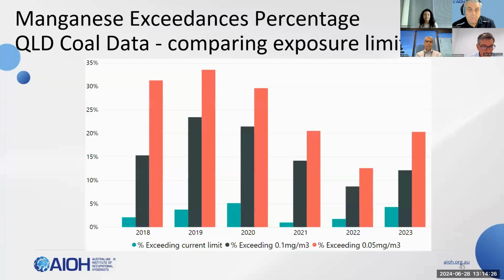If we then look at the proposed limit that comes into effect in December 2026, in black, which is 0.1 milligrams per cubic metre, you see it goes from about 15 to 20%. And if you then look at, as I mentioned earlier, the rule of thumb, good hygiene practice of controlling exposures to 50% of the OEL, that would then be 0.05. It gets up to around 20 to 30%. So it's relatively high. And then if you look at the application of shift adjustment, it ends up being around about 4% at the current limit and about 20% at the new limit that comes in 2026. So the shift adjustment doesn't make a big difference. We then have a look at the impact on nickel.